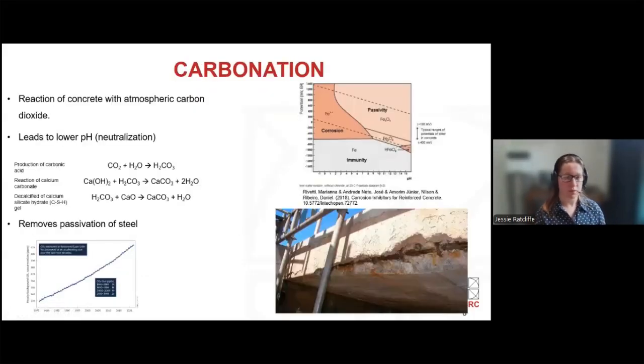Key tests we need to complete to understand the deterioration state of an existing reinforced concrete structure is the carbonation depth. Carbonation is the reduction of pH, also known as neutralization of the concrete due to ingress of carbon dioxide from the atmosphere. During this process, carbon dioxide infiltrates the concrete, reacts with the calcium hydroxide in the cement paste. We've just got some equations outlining this process here. And overall, that reaction lowers the pH of the concrete.